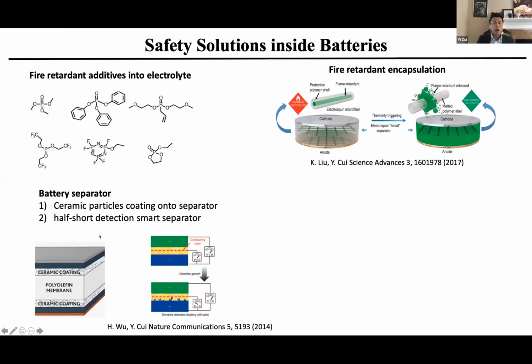And we also think about the idea that shorting is an important trigger of the battery safety problem. Can we do something about this? What the industry already uses is ceramic coating onto the separator to enhance its stability against shorting. A few years ago, we also came up with an idea: inside the separator, you have cathode and anode inside the separator, having a lithium metal detection, half-short detection. If the shorting has happened halfway, you detect it, and make sure you don't do the battery charging anymore, to avoid the shorting continuing to grow to fully short the batteries.